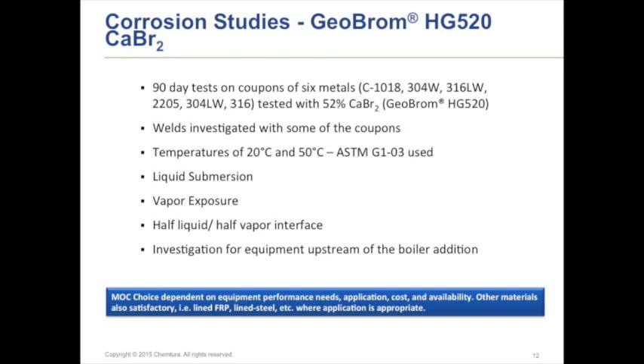The air heater, again, this is where most of the corrosion was demonstrated. Most of it was at the cold end. So again, the question there is what's going on with the operation of the unit as far as temperature. But basically, the other part of that they found was that there really was no corrosion exhibited when they used enameled baskets. Now, they didn't have enough data to really recommend using that, but for the most part, with our experience as well, dealing with hydrobromic acid and other materials that are corrosive, as long as you do have a reliable coating that's being used in the right application, that will help with corrosion issues.